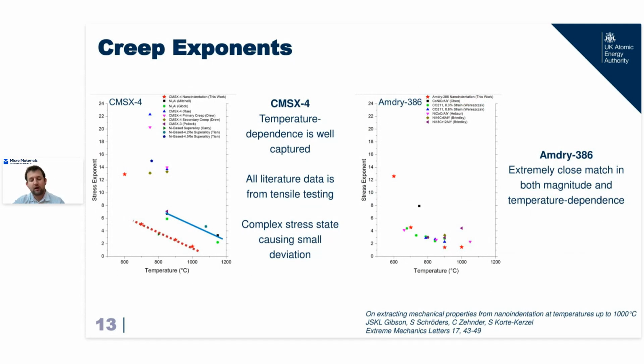Now, ideally, that whole period is not just to make your modulus sensible. Ideally, it will give you something that is vaguely related to creep properties in reality. And we see actually here that we don't do too badly. This might be luck, but we don't do too badly. In our reference CMSX4, a nickel superalloy, we do capture the temperature dependence very well. You can see the literature gradients marked out in blue compared with our indentation gradients marked out in red. We do have a shift, probably because of that complex stress state, but we do capture the temperature dependence of our creep stress exponent.